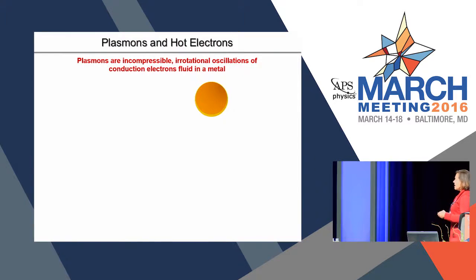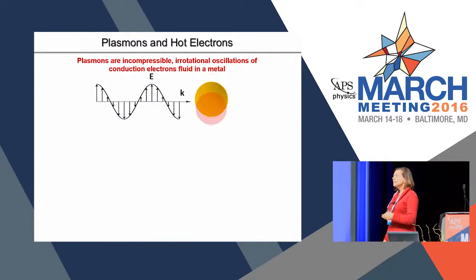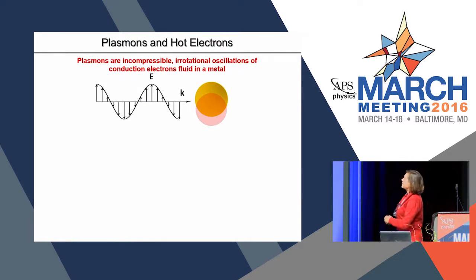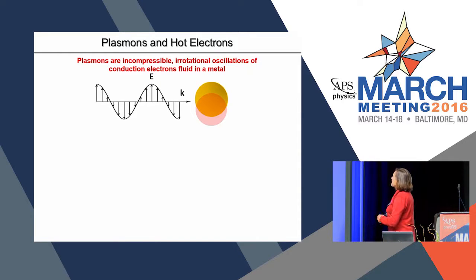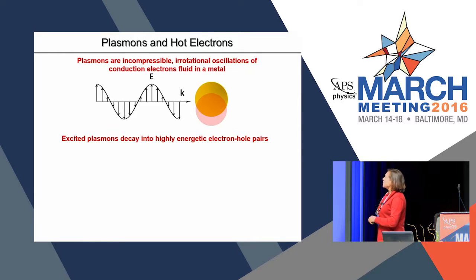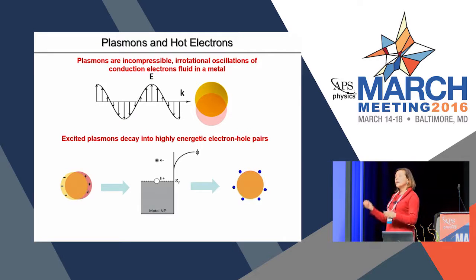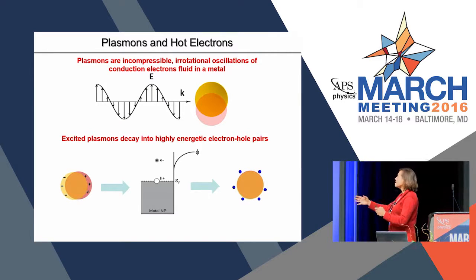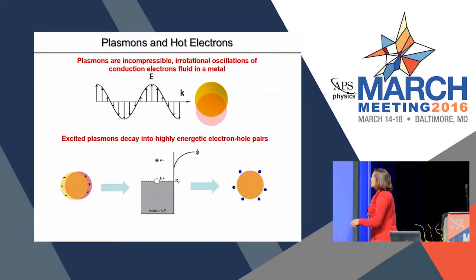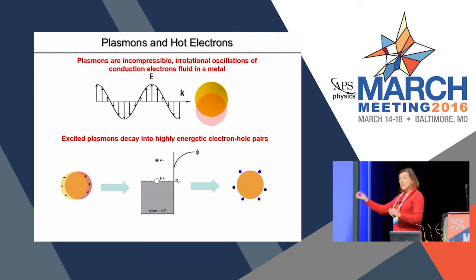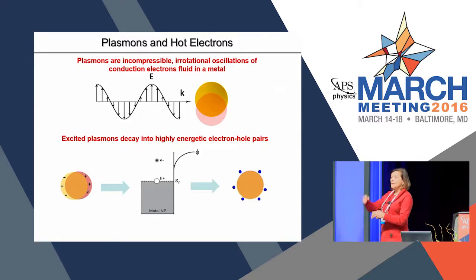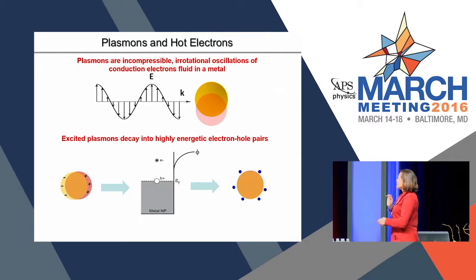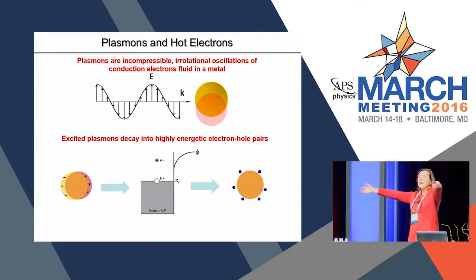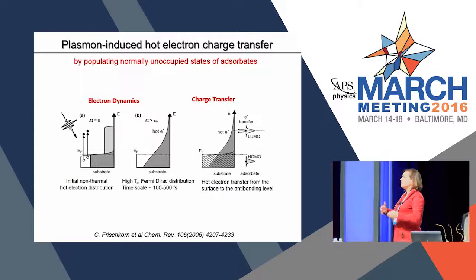So another thing that plasmons do, so we think of these as sort of small optical objects that act like antennas. But another thing that they will do when we excite a plasmon, so that's my little cartoon of an optical excitation of a gold nanoparticle and the conduction electrons. Once we excite a plasmon, the plasmon can decay several different ways. It can decay radiatively by scattering a photon. It can also decay by the excitation of an electron-hole pair. And so the electron-hole pair corresponds in energy to the resonance, to the energy with which I've coupled light into the nanoparticle. And if I excite, say, for example, a cold hole and hot electron, so whether the electrons and holes are hot and cold depends on the electronic structure of the metal, but in a simple metal like aluminum, if I excite the electron-hole pair, the electron will be hot. It will actually extend out from the surface, and so it's available now to perform other tasks.